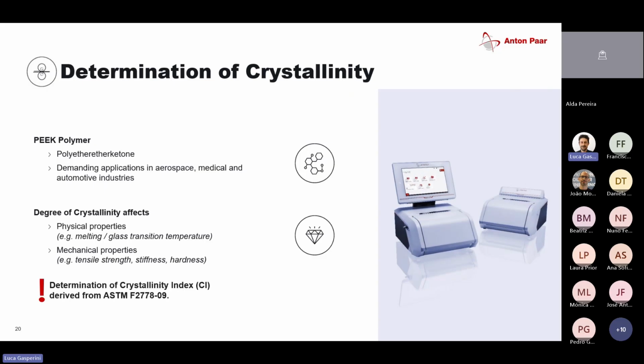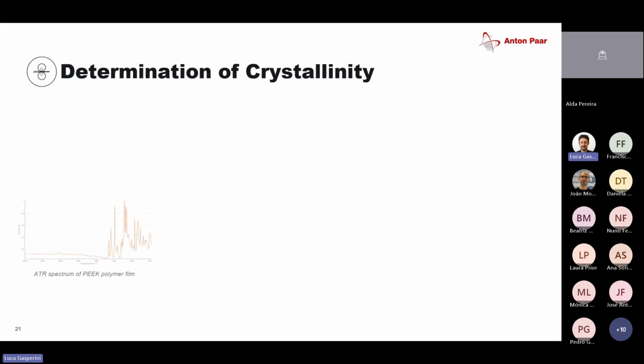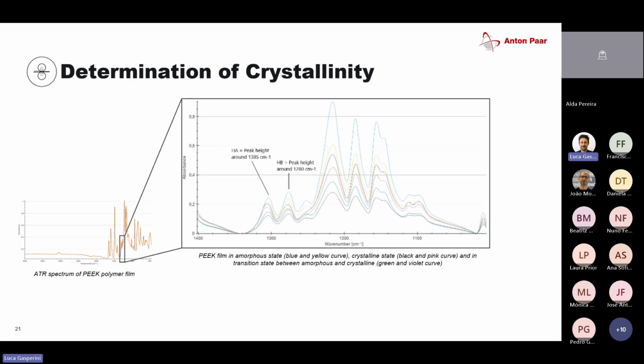So how did we do that? We were using the ASTM F2778. So we were recording a spectrum. You cannot really tell much by just looking at it, so we're just going to zoom in a little bit. And what we are typically interested in is these two peaks. So we're interested in the peak height. We record the peak height of both peaks, and then we use those as a ratio. And from the ratio of HA, the peak height of peak A, and the peak height of peak B, we can actually determine the level of crystallinity.